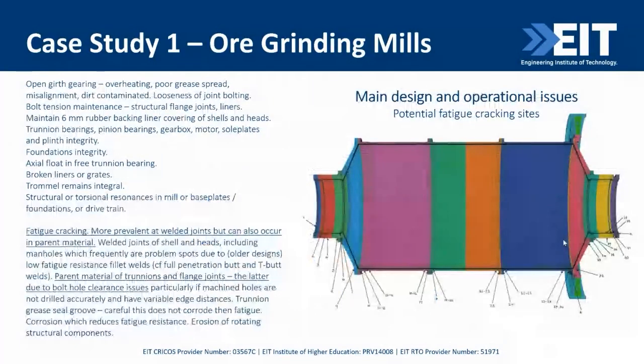So what you need to do, I mean, obviously top left there is major problems. On the bottom is fatigue, and what you've got to do with fatigue is go through every potential hotspot of the trunnions, heads, shells, to work out at your 40% charge, specific gravity around 5, whatever the ore is. So every rev, 15 RPM, you make sure that cycle, stress range cycle, compression to tension, is not creating you a fatigue problem.